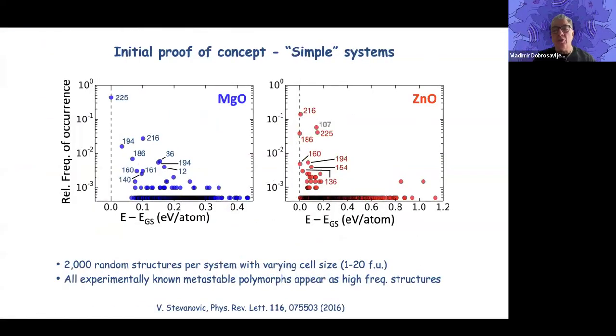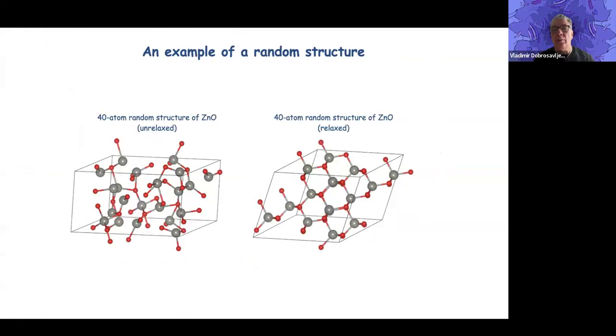Couldn't you say, how do you actually generate the initially random positions? Because it seems to me from the picture they are clashing with each other. They're not completely, you know. Okay. So let's call it quasi-random, quasi under quotations. So what we would do, we would choose random a, b, c, alpha, beta, gamma lattice parameters within some reasonable bounds. So we will not allow angles between unit cell vectors that are 1 degree or things like that. So we will create more or less some kind of box that is reasonable.